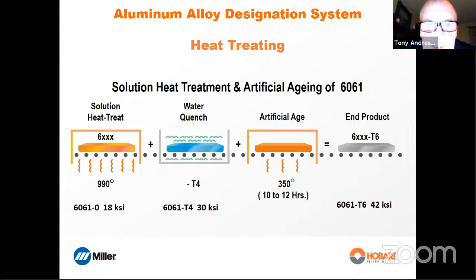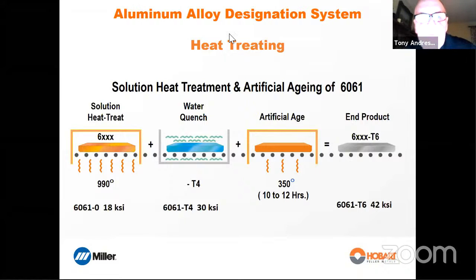Now let's take a look at the heat treatable alloys, where strength is increased through thermal treatment. One of the most common materials out there in terms of heat treatable alloys is 6061. It's used all the time, and this is why I chose it as an example. If we take a piece of 6061 in the O temper, which is the dead soft condition, its tensile strength is 18 KSI. All right.